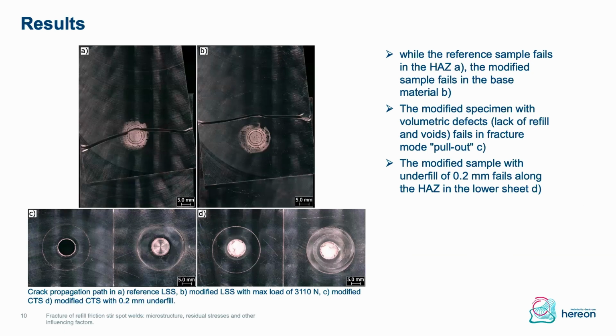This is the fracture which results from the different configurations. On the left-hand side, you see the reference lap shear sample where the crack initiates where we would expect it, in between the stir and the thermomechanically affected zone, and then propagates horizontally through the sample. While in the modified lap shear, we see that the crack does not appear in the area of the spot weld, but in the base material. So this is also the reason why we haven't done the underfill step for lap shear, because we didn't see the crack appearing close to the spot weld.